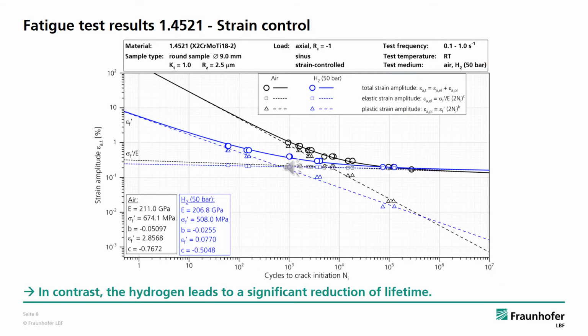The situation is quite different, however, when the test results are plotted in the form of the epsilon-N curve. This plot of the total strain against the number of cycles to crack initiation shows a significant influence of the hydrogen. At the upper load level of 0.8%, a factor of 26 in lifetime reduction under hydrogen compared to air can be observed. This life duration reducing factor decreases with decreasing strain amplitude. At the lowest load horizon of 0.2%, the lifetimes under hydrogen and air hardly differ anymore.